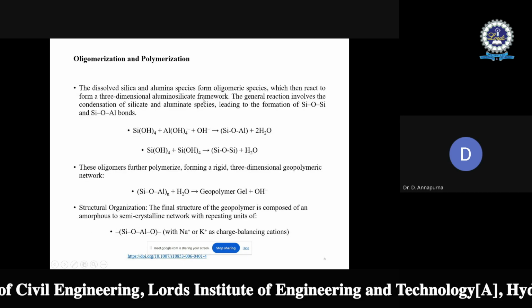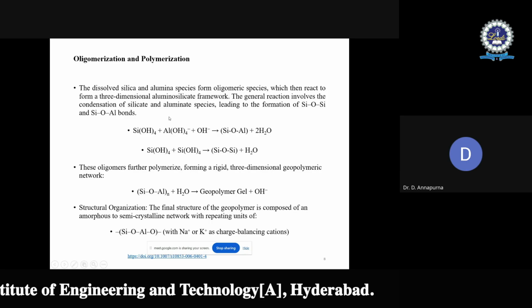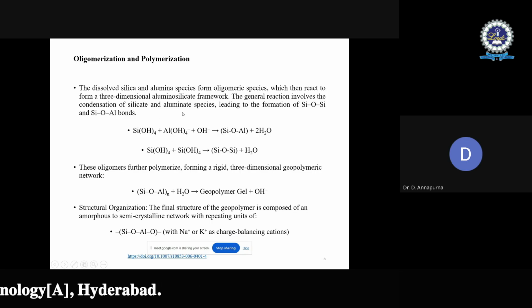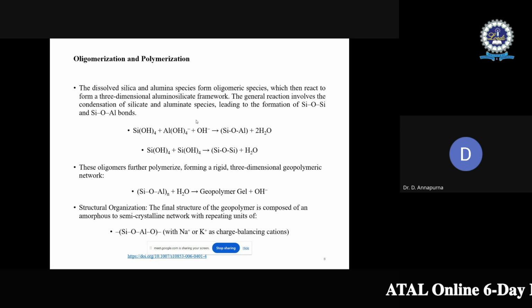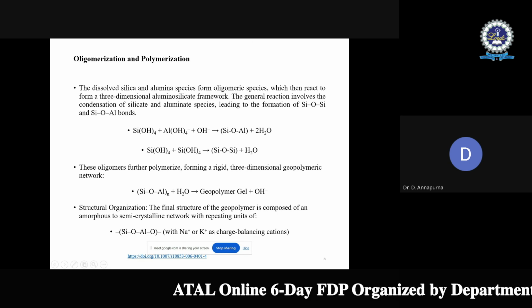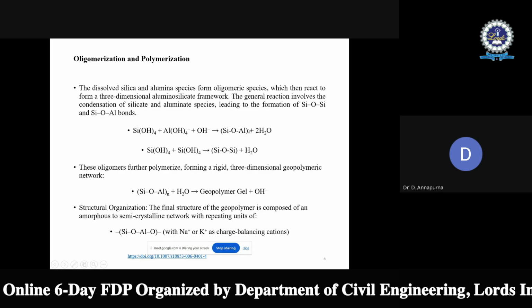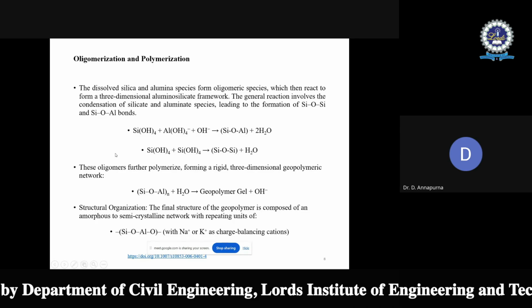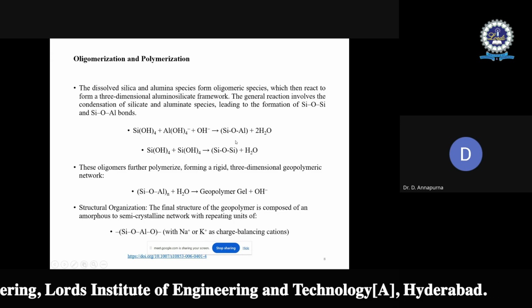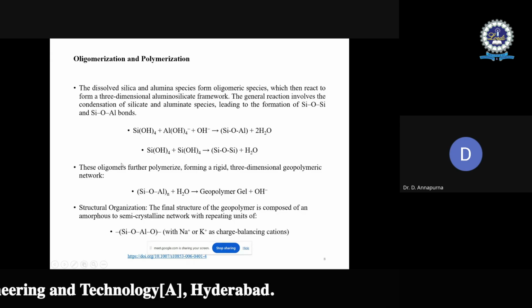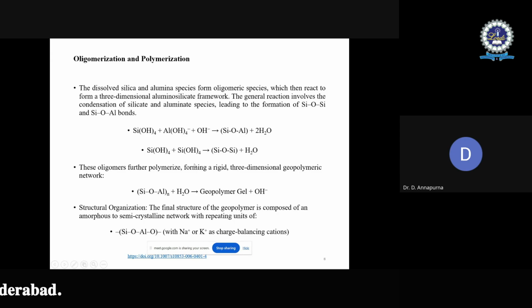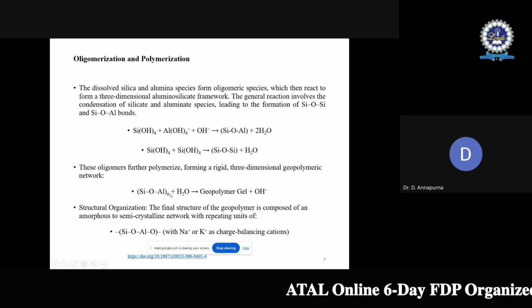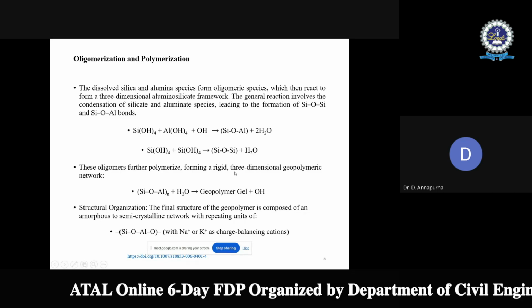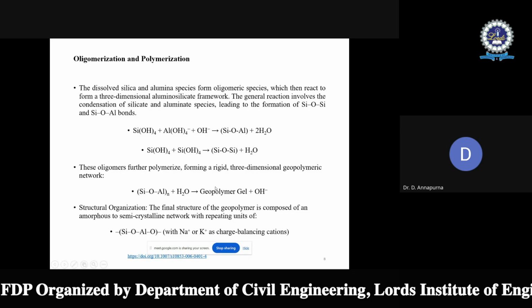A three-dimensional aluminosilicate framework. If you look at the silica and alumina, when they are again reacting in the presence of this alkali solution, they will be giving a three-dimensional structure: silica, oxygen, aluminate, silica, oxygen, silicate. So this oligomerization is the three-dimensional structure formation. These oligomers further polymerize, forming a rigid three-dimensional geopolymer network. Let us say this silica, oxygen, aluminate. Again, it will have a polymerization process and it is going to give a three-dimensional geopolymer network.